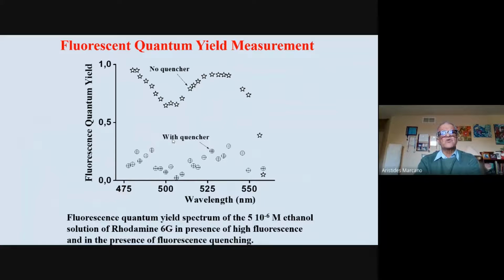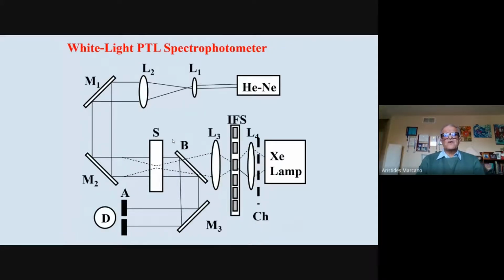Anyway, you can use quenchers to eliminate fluorescence. If you use a quencher and do the same experiment, you can see that your quantum yield reduces substantially. So the quencher just kills the fluorescence. You can see that now the dominant effect will be the thermal lensing because there's less fluorescence. But we use a white light spectrophotometer, so that's a good thing, that you can actually do this using a lamp.